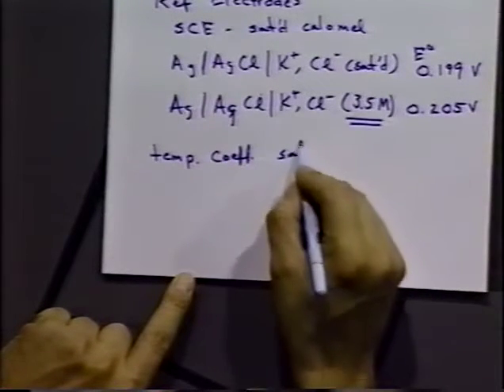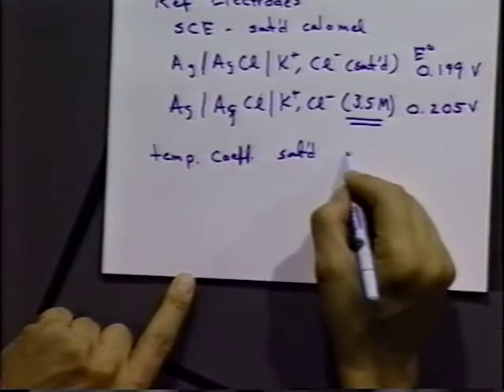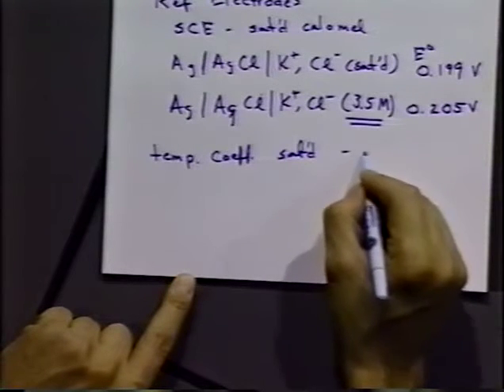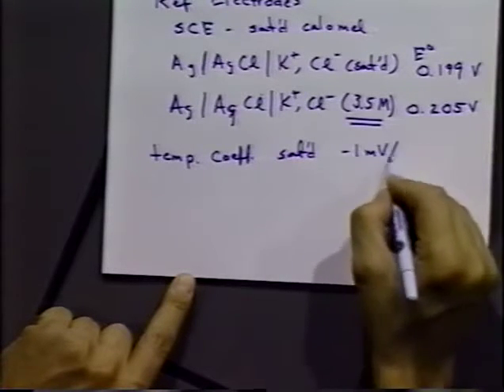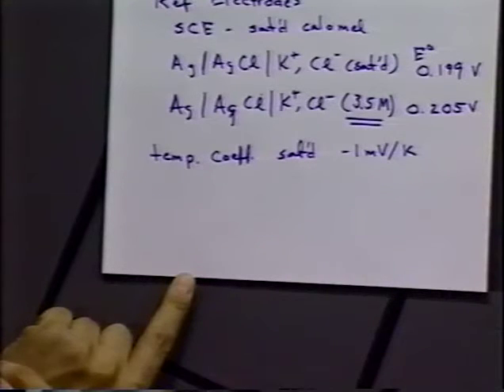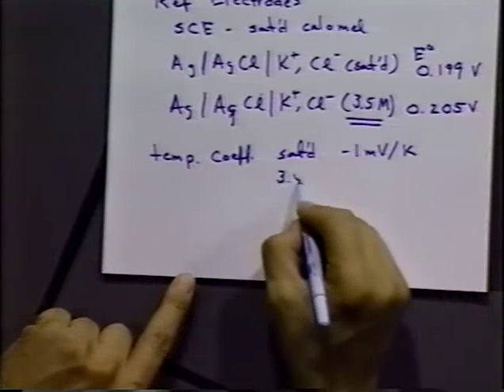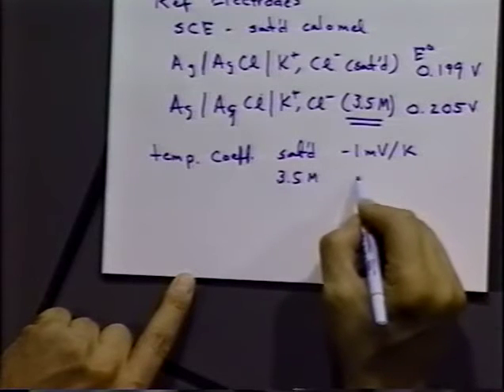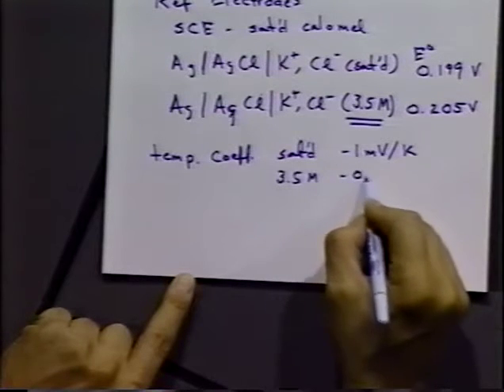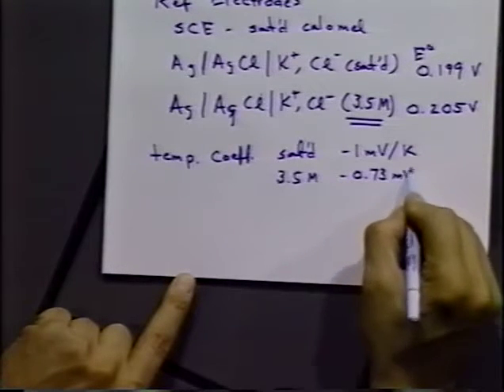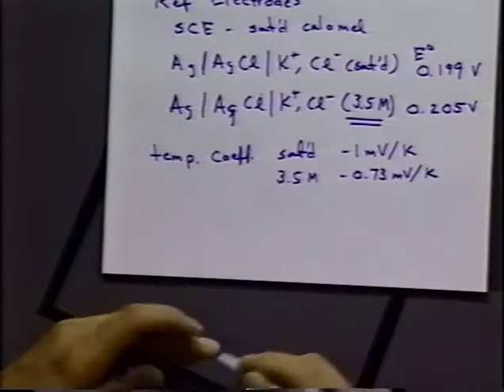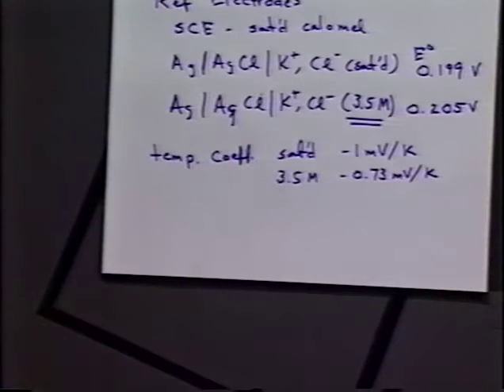And for the saturated system of silver-silver chloride, it turns out that the temperature coefficient is about minus one millivolt per degree Kelvin. And for the 3.5 molar solution, it's about minus 0.73 millivolts per degree Kelvin. In other words, there is quite a difference in the temperature change of the potential change with temperature for the two systems. And it turns out to be important.